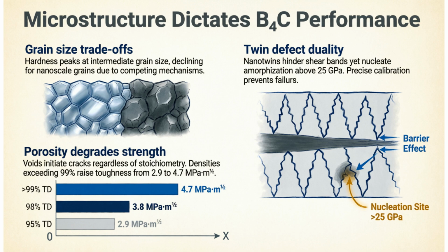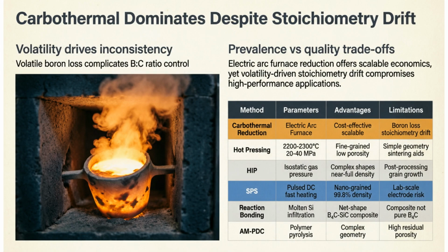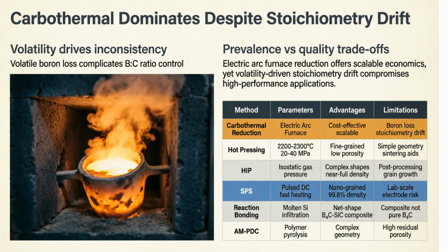While porosity degrades strength, twin defects can hinder shear band formation, though they may also nucleate amorphization if not precisely calibrated. Carbothermal reduction is common due to its scalability, but boron volatility often leads to stoichiometry drift, which can compromise the quality needed for high-performance use.